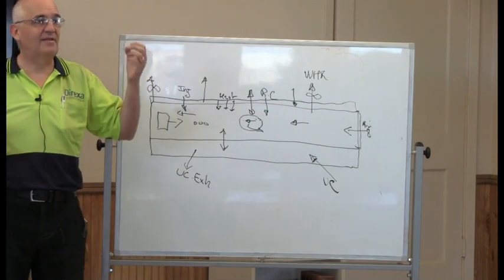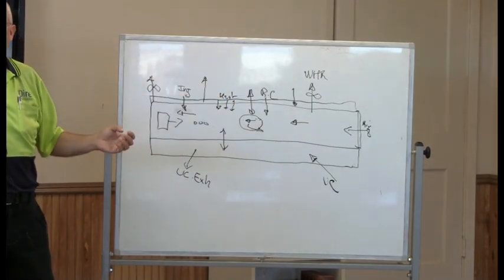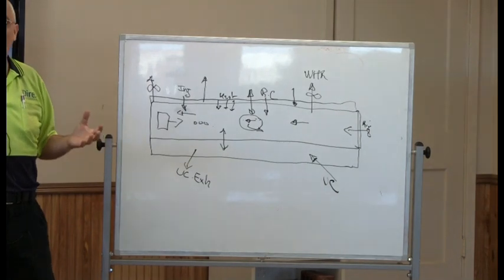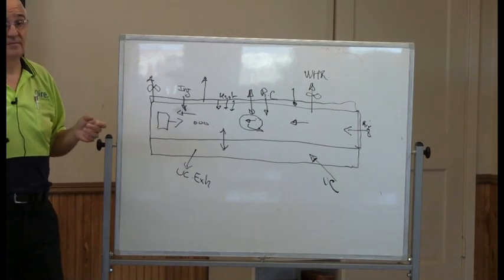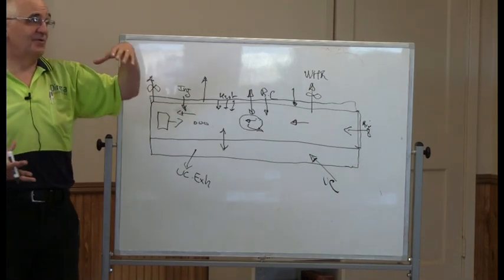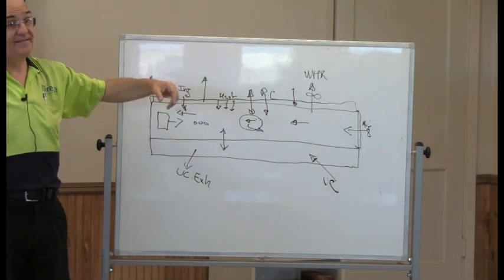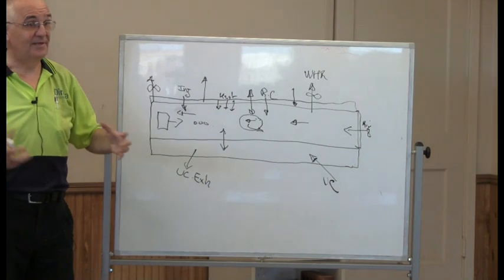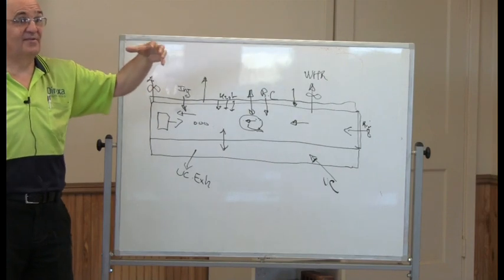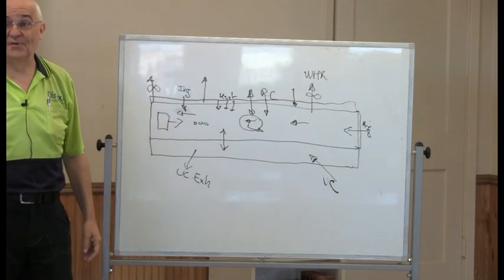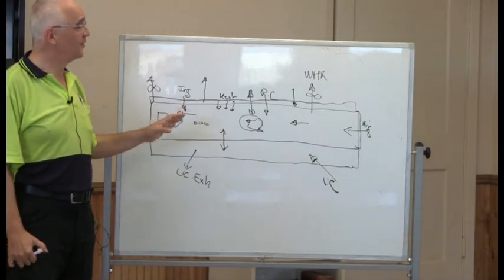So you can't compare the air from the waste heat with the air from the supply at the end of the kiln in volume. You have to compare in mass. You know that in the hot waste heat recovery, the speed in that duct is big, because that pound of air is at 1500 Fahrenheit, and it occupies a big volume. So we're going to talk about mass of air.